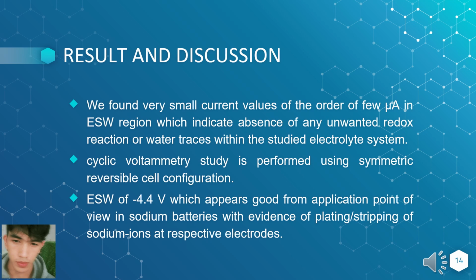This electrochemical stability window of 4.4 volts appears good from an application point of view in sodium batteries, with evidence of plating or stripping of sodium ion at the respective electrode. Many researchers have reported similar sodium ion movement using polymer gel electrolyte membranes and reversible sodium electrolyte systems.